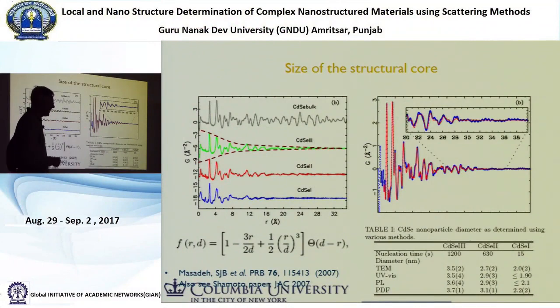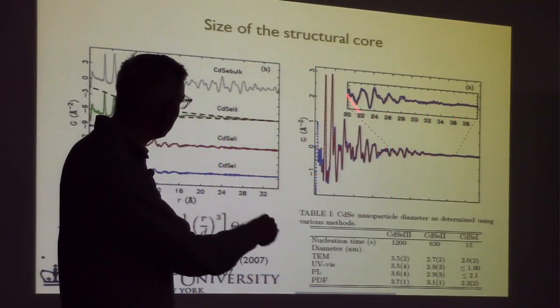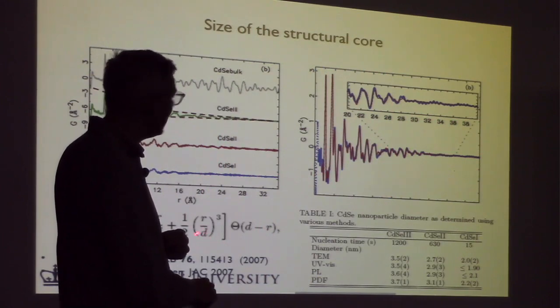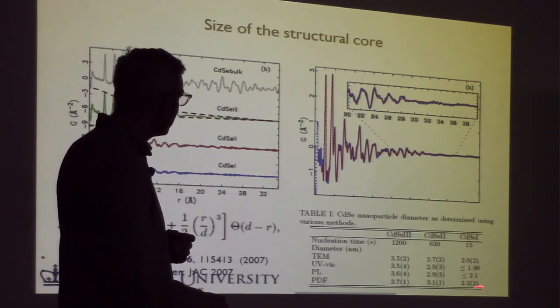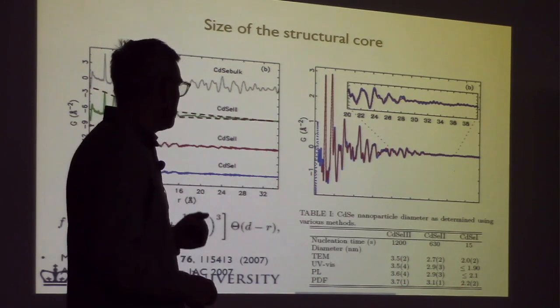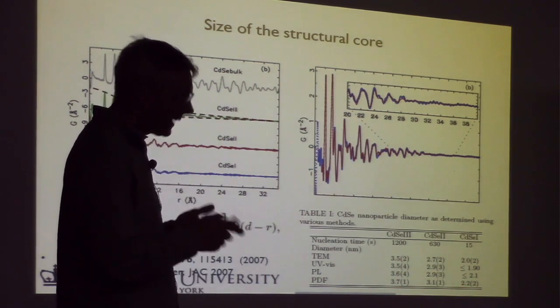So we can fit structural models to the nanoparticle, we can extract stacking fault defects, and we can measure the size of the nanoparticle. By using this function here, which is actually the characteristic function for a sphere. So if we assume that the nanoparticle is spherical, we have an analytic mathematical form for its shape. And so we can multiply our model by that term, and then it has one parameter, d, the diameter, so we can extract the diameter. We get very good values for the diameter. So we can get the structure, we can get the defects, we can get the size.